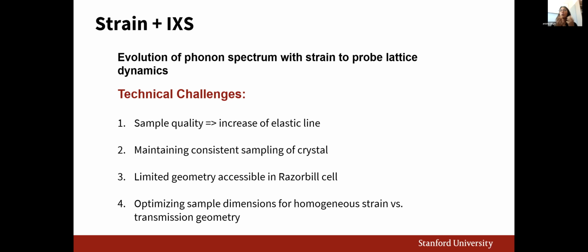Also, as we're working with a small beam, and as we're constantly moving our sample with strain, it's a bit non-trivial, right, to maintain consistent sampling of our crystal volumes, and to keep in mind as we're taking these measurements. Something else that I want to touch on is the way that the sample is actually mounted within the Razorbill cell. There's a series of screw plates that we have to use to actually fix that substrate, which I showed on the previous slide, which is going to result, especially when you're working in transmission geometry, in a sort of reduction of access to our sample from the beam. Something else that we had to sort of contend with.